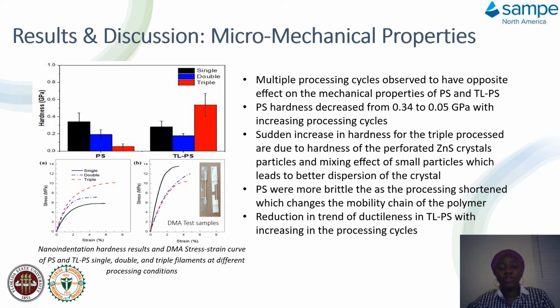The composite at the 3rd extrusion shows a higher hardness compared to the 2nd, and this sudden increase is due to the hardness of the zinc sulfide, and shows the mixing effect of the zinc sulfide particles, which shows there is an evenly dispersed particle within the composite, and this leads to the sudden increase in the hardness of the triple extrusion for the composite.